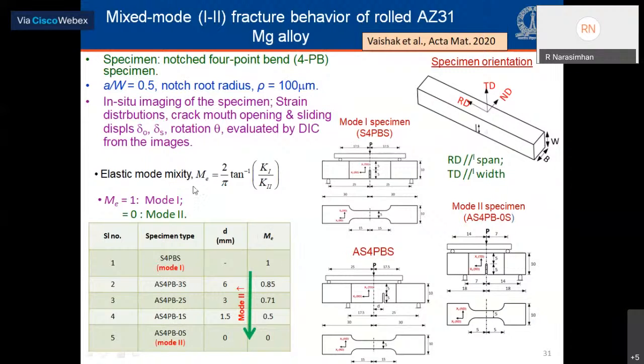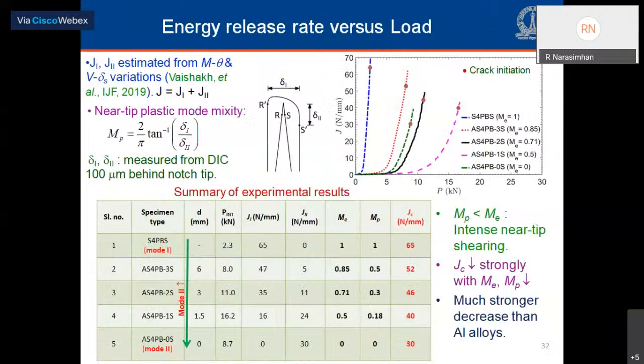And this is quantified by what is called the elastic mixity parameter ME, which is defined in terms of the ratio of K1 to K2. Now we did optical in situ imaging as we loaded up the specimen, which was later analyzed by DIC in order to figure out the strain distribution as well as the crack opening and sliding displacements.